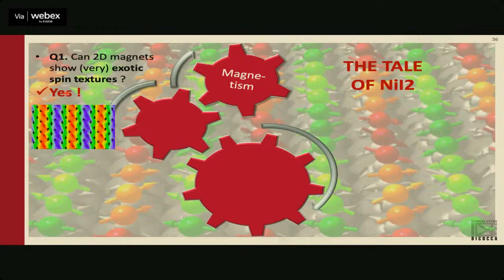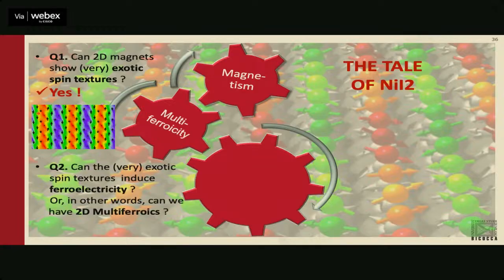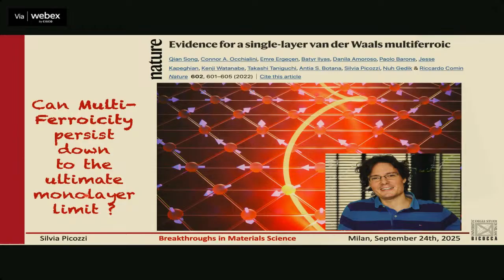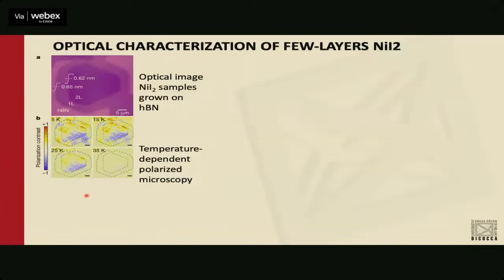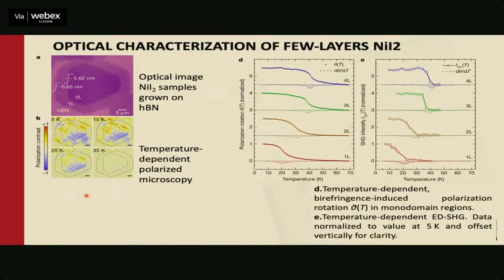So the answer to the first question is yes, I can have an exotic spin texture in 2D. Second question: is this kind of exotic spin texture inducing ferroelectricity? Can I have multiferroicity in nickel I2? This was the question we asked in collaboration with my collaborator at MIT, Riccardo Comin. He's an experimental professor. Riccardo grew exfoliated nickel I2, and then they did many kinds of characterization, including optical and nonlinear optical ones. In particular, they did second harmonic generation and optical birefringence for few layers, let's say 1 layer, 2 layer, 3 layer, 4 layer of nickel I2.